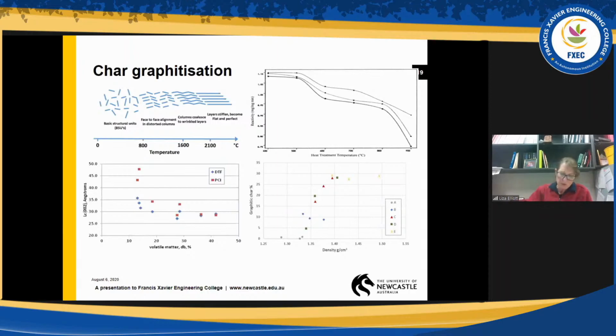LC is the height between the graphitic sheets, and LA is the length of the graphitic sheets. And this figure here on the bottom shows you the difference between chars that were produced in a PCR rig and chars that were produced in a drop tube furnace. And there are significant differences in this area, whereas not so much for lower rank, high volatile coals.